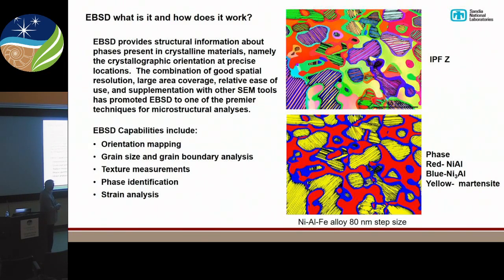We can do texture, of course, if you're interested in the texture of a rolled steel or a rolled material or something plastically deformed, we can deal with that. We can do this phase identification, as you see here. Given a list of phases, we can pick out the ones that match. And then finally, this last one down here, which I won't talk about much today, is the newest thing, strain analysis, where they're starting to measure from point to point the elastic strain and some of the plastic strains within a sample. So it's a technique that's got a lot of different applications. And I think it really has become one of the premier tools for microstructure analysis.